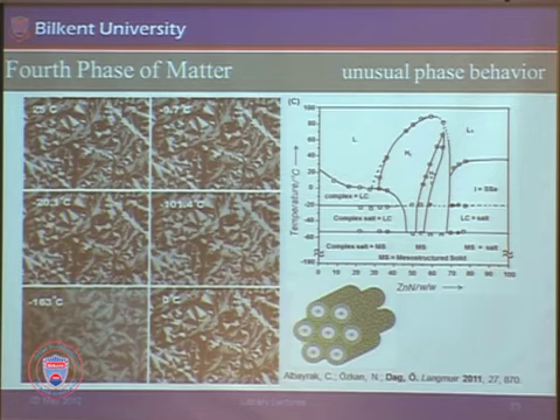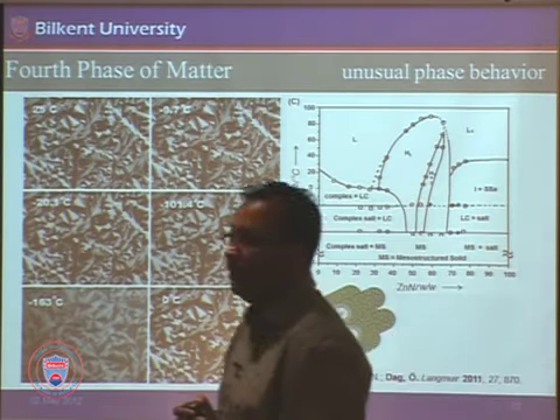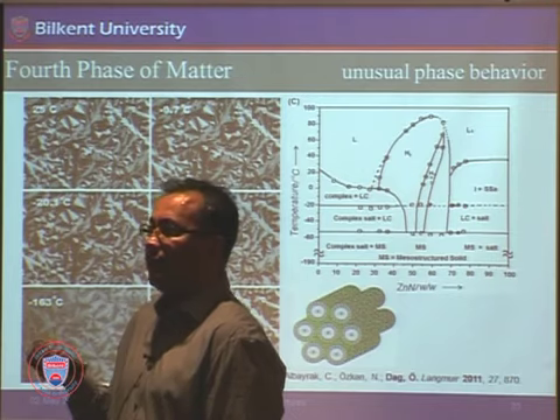This texture is an indication of liquid crystal. Then we cool it to almost -10, still there, nothing is happening. -20, nothing is happening. -101 degrees. We go all the way to liquid nitrogen temperature. The texture is still there. At some point, this region becomes solid, goes into a solid phase, but keeps the structure, never leaches out these salt molecules. If you put any salt in any solvent and cool it down, it will crystallize. Here, when you put it in such a small domain, its melting point drops drastically, such that it never crystallizes, it never freezes.